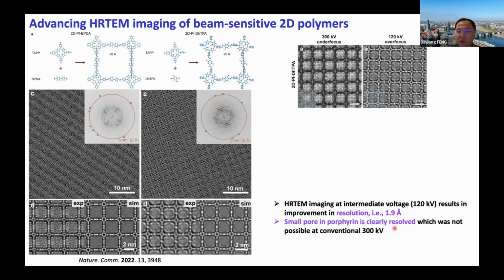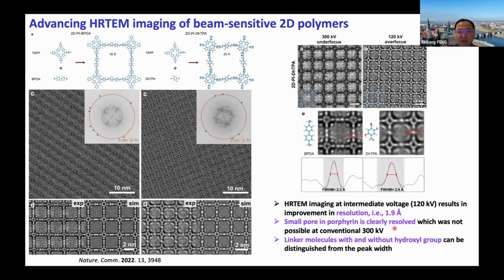Or basically the grain boundary structures, to be probed for these organic crystal materials. And the more recent development with our TEM collaboration partner, which shows that we even can go to atomic level, like you can image the porphyrin molecule. So this is a porphyrin molecule. You can image the bond, this is a benzene ring, this is a biphenyl ring, and this is a single benzene ring. You can image the molecule structures at a very high resolution level. So basically resolution can reach about 1.9 angstrom. And this is really beautiful and very clear proof that we have this well-defined layer materials, with a few layers.